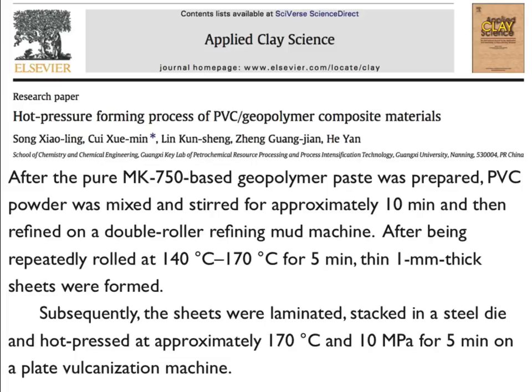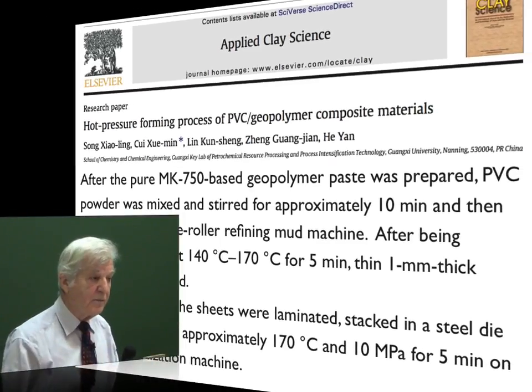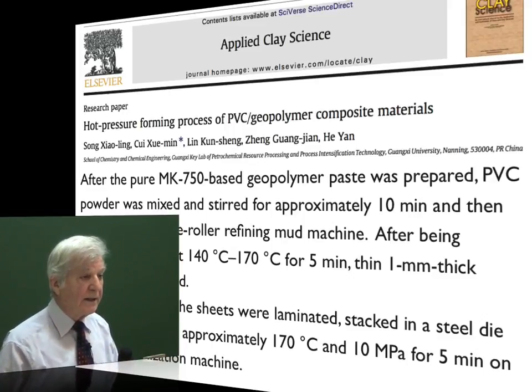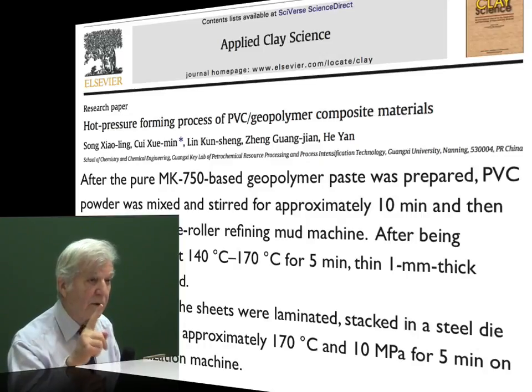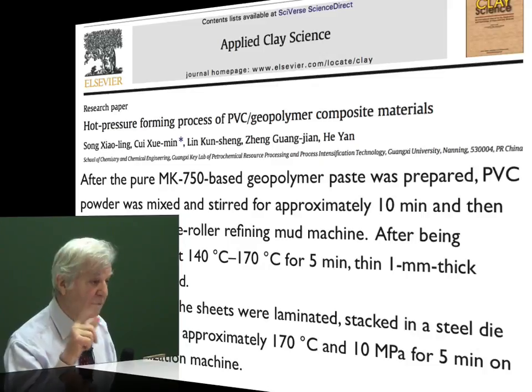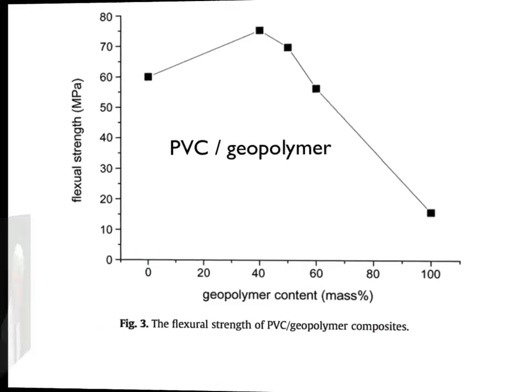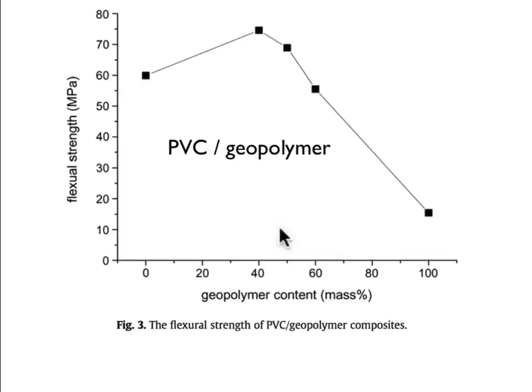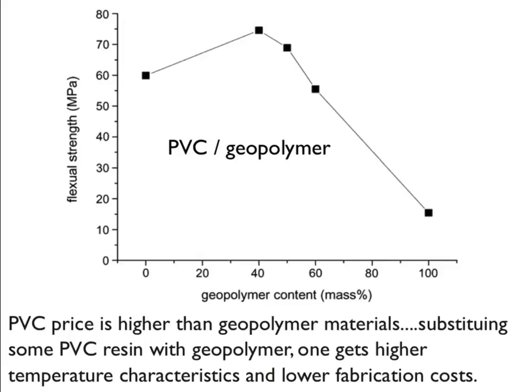Subsequently, the sheets were laminated, stacked in a steel die, and hot pressed at approximately 170 degrees C and 10 megapascal for 5 minutes on the plate vulcanization machine. So they use the thermoplasticity of PVC in order to take the geopolymer in it. It was processed at 140, 170 degrees C, which means the water has escaped. This is what they get: flexural strength increases with geopolymer content up to 40%, and then decreases, so there's compatibility up to 40%. What they write is PVC price is higher than geopolymer material. Substituting some PVC resin with geopolymer, one gets higher temperature characteristic and lower fabrication cost.